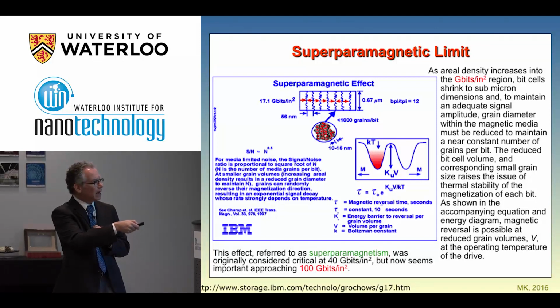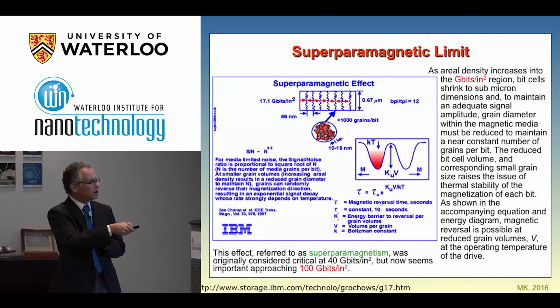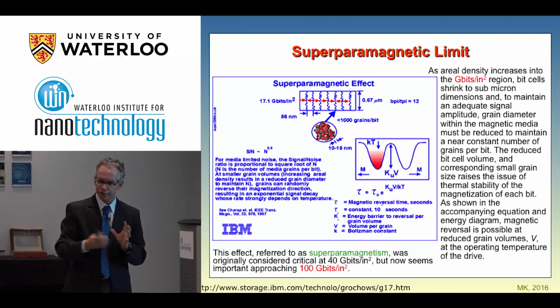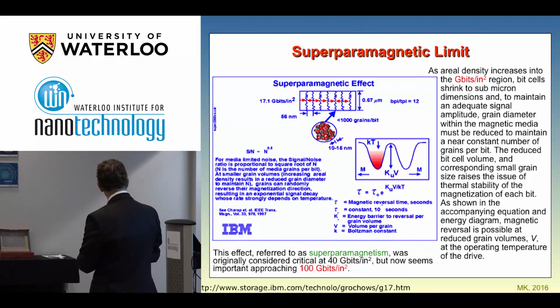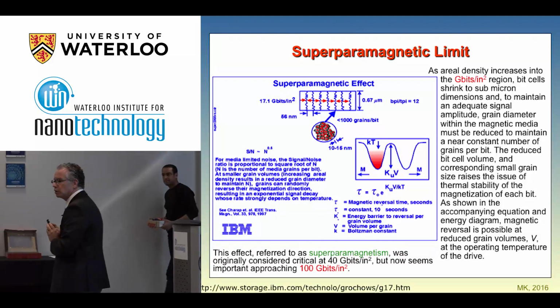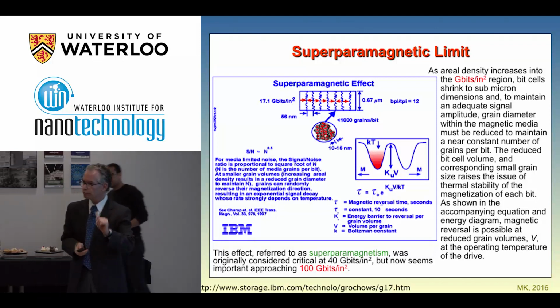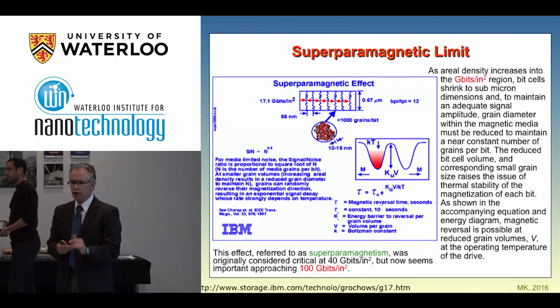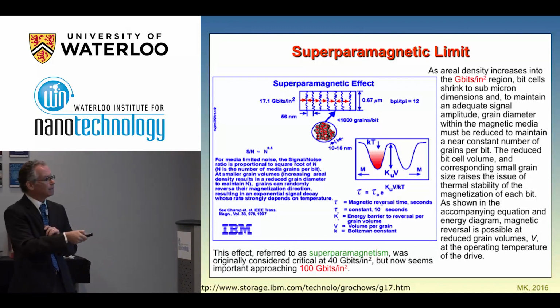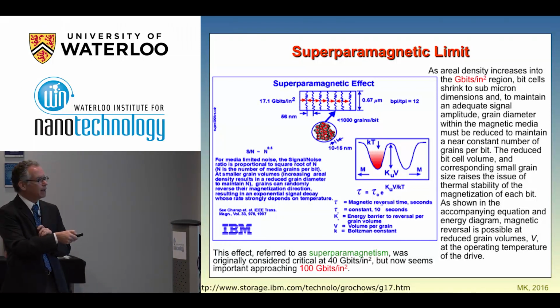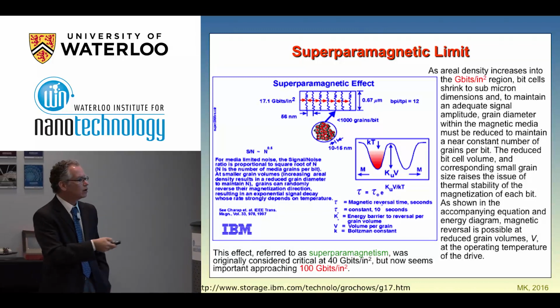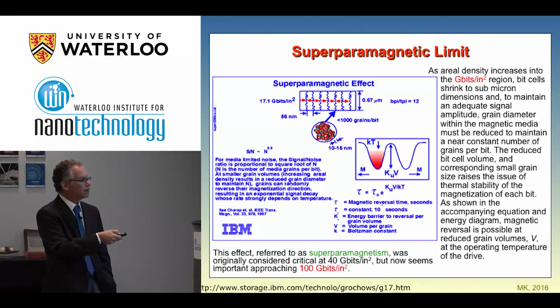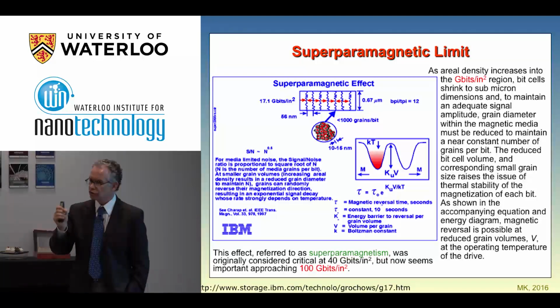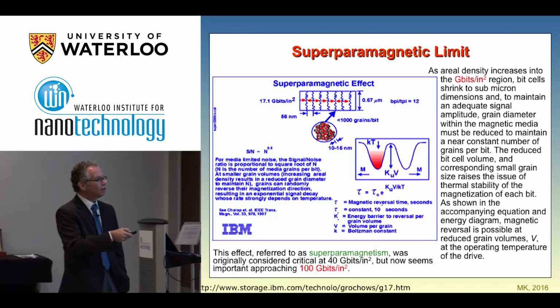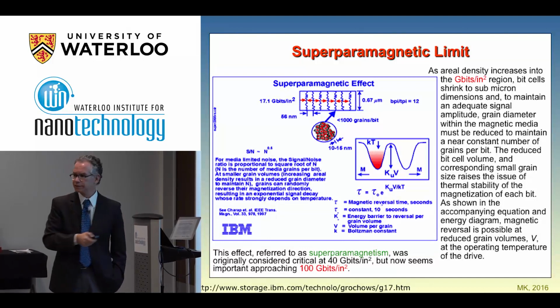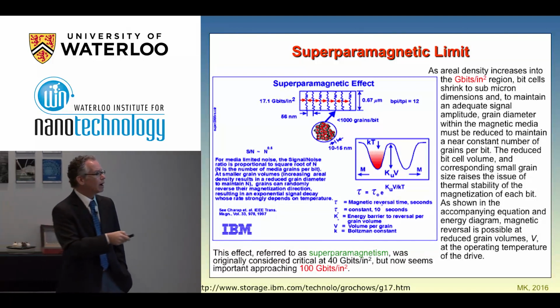But there is an energy barrier here, which is proportional to this entity, which is a density of energy called the anisotropy of the material. It depends on the material's properties. It depends on the shape. It depends on a series of things. But there is a quantity here depending on the material's property. And of course, this is a density of energy, and then you have a volume. So you can see that if you reduce the volume, you reduce this barrier,